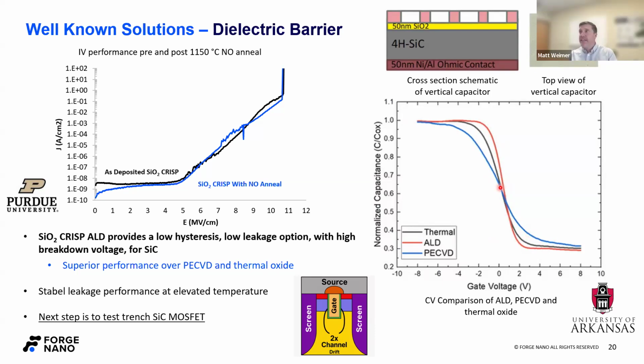Again, this isn't too surprising. People already know that ALD gives a higher quality dielectric than thermal oxide, obviously, or than PECVD. But it's always important to prove it out on the specific device. I'll talk about this a little bit later with hafnium dioxide, but you will see different dielectric film properties depending on the substrate. That means the interface between the ALD film and whatever you're putting it on really matters a lot. Okay, so as one last point here, as some people transition to trench features, ALD is the best solution here, and really the only viable game in town, from our perspective.